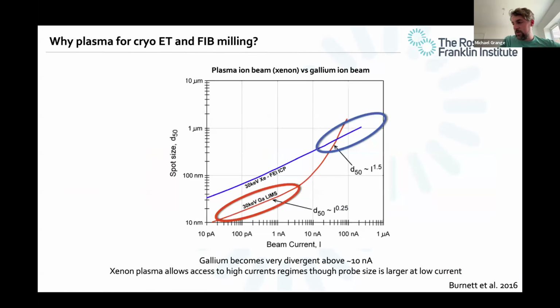So part of the talk title is about plasma ion beam milling. And so why plasma? Gallium is perfectly fine at low currents to mill very thin samples. And this has been demonstrated since 2007 by Mike Marko. Part of the reason why we want to use plasma is because of this blue circle here. As we go to very high currents, gallium becomes very divergent because of the nature of the optics and the extraction of the ions from the tip. Whereas at low current, gallium has a very small probe size.